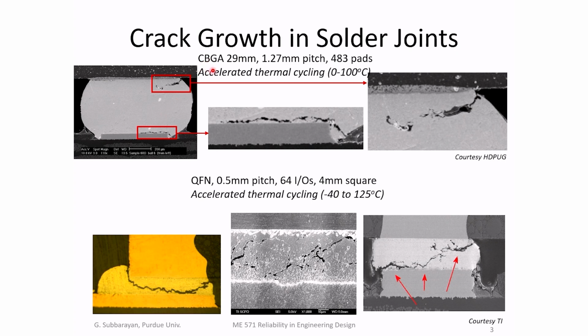This is a ceramic ball grid array component. It's a CBGA, which stands for ceramic ball grid array. There were 483 solder joints on that package and 64 in this particular package, and they were thermal cycled from 0 to 100 degrees C, and this is from minus 40 to plus 125 C. And these conditions depend on the intended use environment of your product. So for office use, 0 to 100 degrees C is a typical test condition. More aggressive use, you might have minus 40 to plus 125. If it is in avionics, you might couple temperature cycling with random vibration.